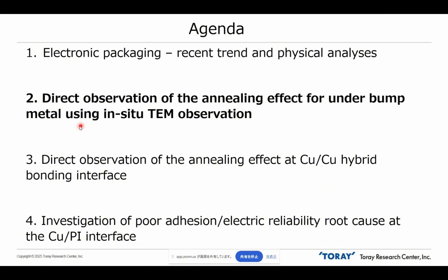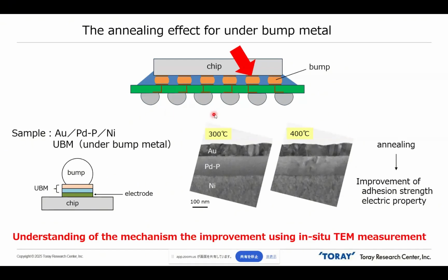So today I'd like to show some typical examples. The first one is direct observation of the annealing effect using in-situ TEM observation. In this topic, we'd like to focus on the interface between the bump and the IC chip. Here is a metal layer. The under bump metal is here. This test sample has a nickel, palladium, and gold multi-stack structure.